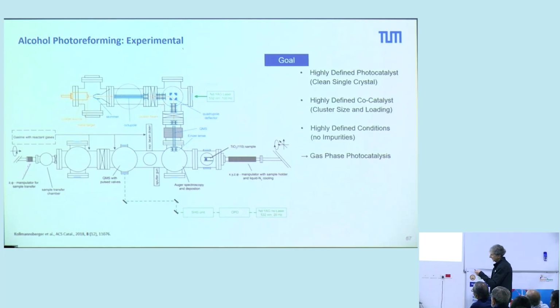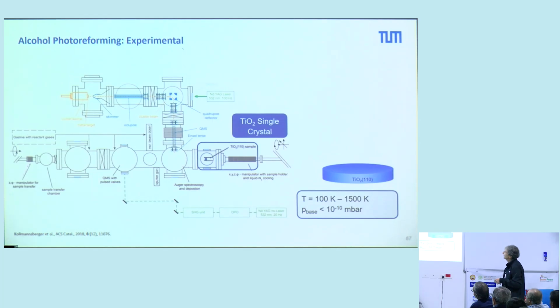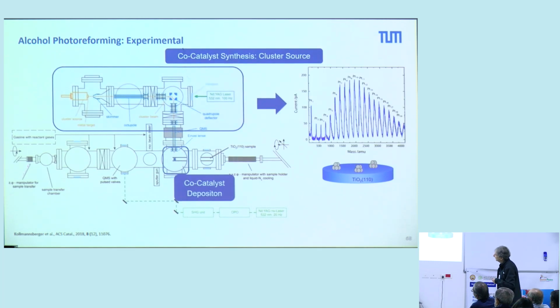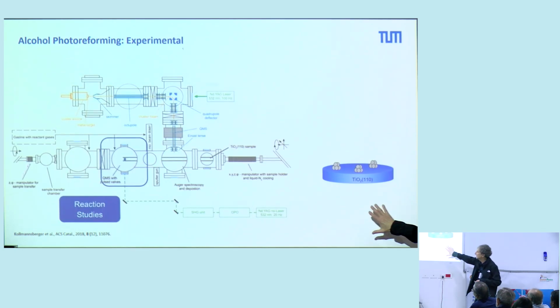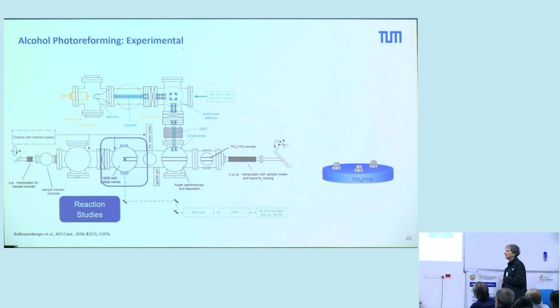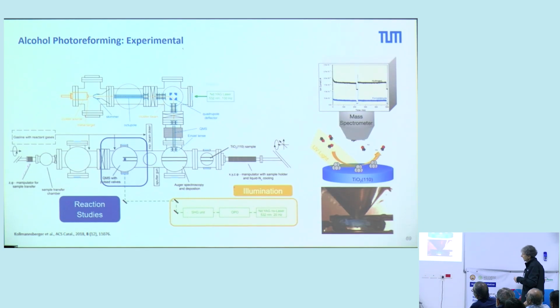Again, you see here the setup. We have a laser vaporization source with which we are producing these clusters. Then we have the ion optics, a quadrupole mass spectrometer, and then we can deposit these clusters on a titanium dioxide single crystal, which we can heat, and we can deposit different sizes of these platinum clusters. And last but not least, we have an OPO laser with which we can stimulate a photocatalytic reaction. We prepare these samples with clusters, expose them to ethanol or methanol, then turn on the laser, and in the first experiment, we simply measure the products that are formed on these photocatalytic systems.